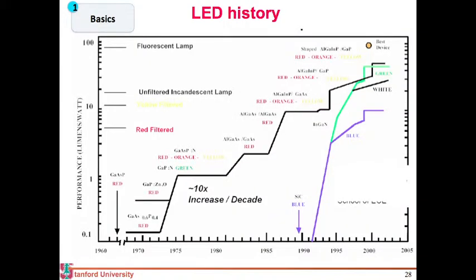This shows the progress map of LEDs: red, blue, and green. The blue really arrived in 1995 and since then their efficiency have been improving, but it kind of saturated again around 2000. Now there has been some recent progress again made by the same guy where he again invented a few things. He got rid of polar planes, and we heard more about it on Monday. Now that road map again has started going up. It is compared over here with respect to some of the incumbents. Incandescent bulb, as you can see, has a maximum efficacy of around 10 or 20. Fluorescent bulb goes above 80, the best HID lamp goes up to 150. The LEDs currently are above fluorescent but slightly lower than your discharge-based lamp.